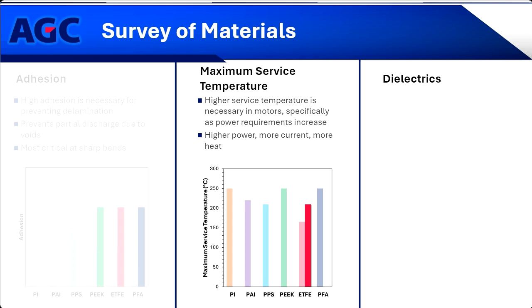It hits right around that 200 degrees Celsius mark, where we can show equivalent performance as it relates to maximum service temperature, which really shows that we can now promote these materials into this application space where the temperature requirement is a little bit more strict than some other areas.